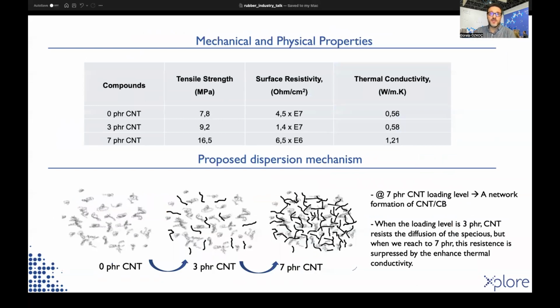In order to further understand the dispersion mechanism of carbon nanotube and carbon black, we conducted electrical resistivity and thermal conductivity measurements. In both cases, the conductivity of the sample increased drastically at 7 PHR carbon nanotube content. The increase in thermal conductivity also explains the increase in cross-linking density due to better homogenization of the heat during the vulcanization reaction. As a result of the formation of the network structure and the higher cross-linking density, we observed better mechanical properties at 7 PHR carbon nanotube content.